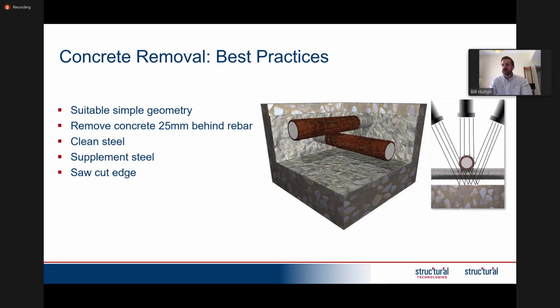And the reason why we say supplementary steel is that it's very rare that you would actually remove steel from a structure. You always just add in additional steel. Obviously, whenever you're adding in additional steel, it's important that you get sufficient development length. So that's the overlap between the new bar and the old bar. If there's not sufficient development length, then you may need to drill in epoxy anchor dowels to provide that development length.